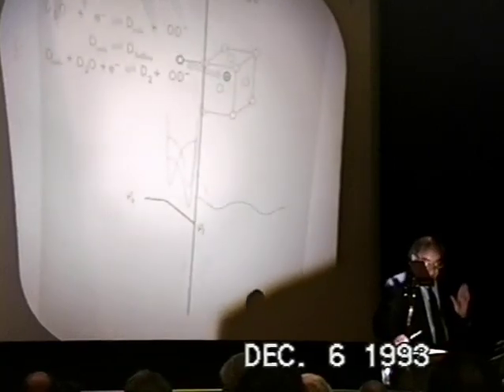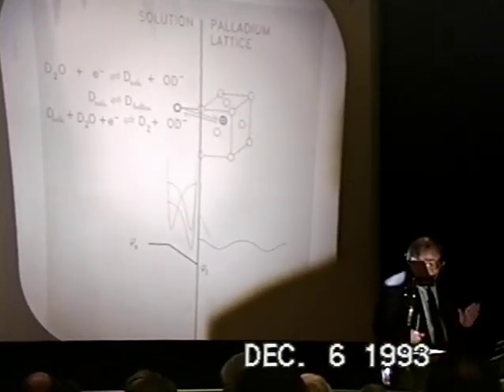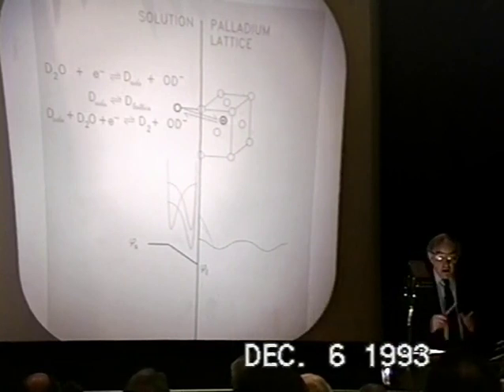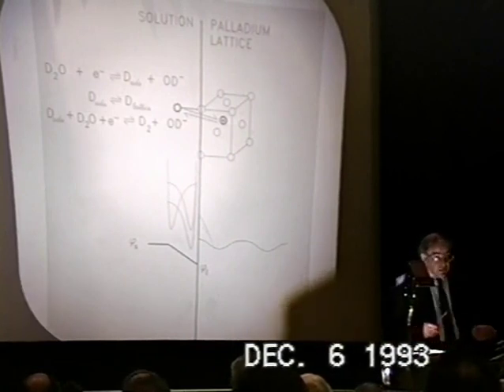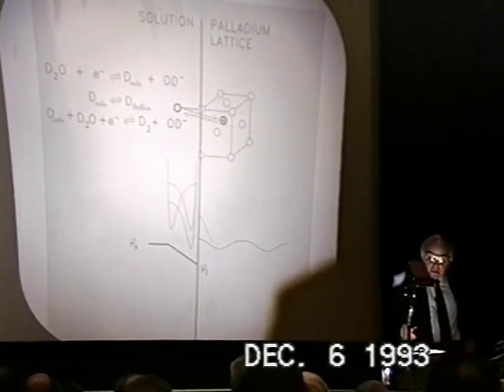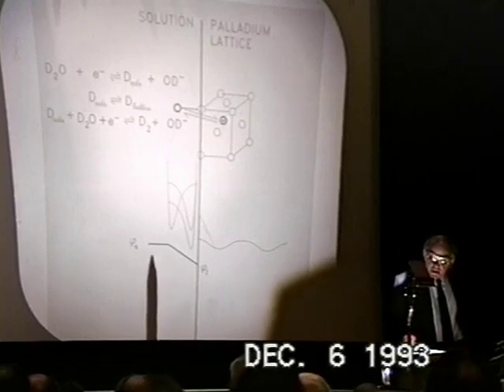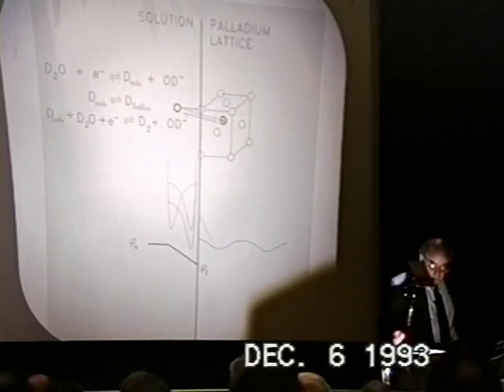But of course, the most economical way in which we could apply a galvanic potential difference was not in the wire. If you think about it, it's quite hard to get a very high potential difference in a wire, although in principle you could achieve something like 10 kilovolts per centimeter theoretically. So we decided to be more modest and do it at the electrode solution interface.